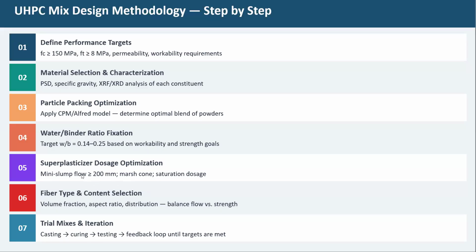And particularly when we are finalizing the superplasticizer and dosage, it is essential to attain a minimum mini slump flow of greater than or equal to 200 mm. But if you are getting a flow of 220, 230 mm, which is very good, but don't go beyond 250 mm, because that leads to segregation or bleeding of the materials as well. So keep the flow less than or equal to 230, and that would be more than sufficient. But don't go anything less than 200 mm.